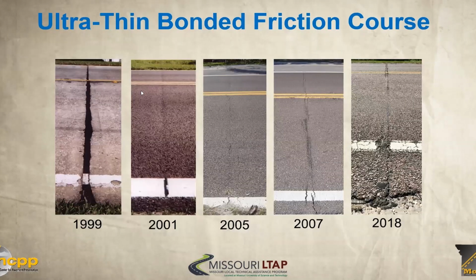And typically you would have a lot of cracking come back through this at less than 1 inch. But you can see here through the ages, where I've been able to follow this same joint, just how effective it's been. I actually was out there, I didn't get a picture of it, in 2020, and it still looks very good.